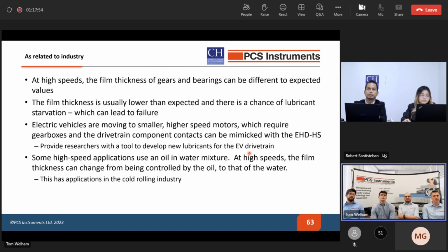Another example where high-speed behavior is different to lower speeds is that of emulsion lubrication. So this is another example where the high-speed EHD can help you understand more about that application. In that specific case, the effective viscosity of emulsions can greatly reduce under high speed conditions, close to that of water.